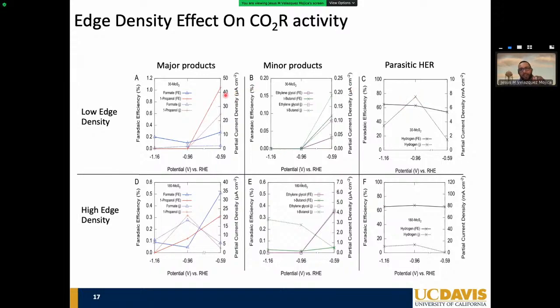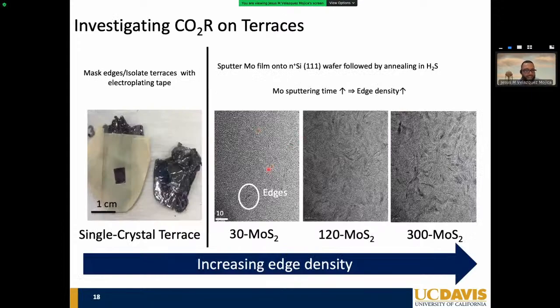But it's still interesting that we are producing propanol when we have a sample that has little to no edges versus a sample that has lots of edges on the surface, right? If you remember the paper that I showed you on how to improve the hydrogen evolution reaction by increasing the number of edge sites, this is basically the opposite. So we were excited about this. And then we said, well, is there a way for us to expose a surface that has little to no edges? And we did that by using chemical vapor transport to do classical